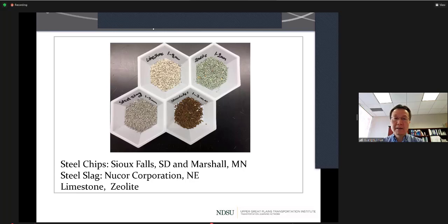So during the batch experiment study, we selected 4 materials, including limestone and zeolite. These are the 2 natural materials that are readily available. And these 2 materials have been evaluated as stormwater filtration materials for phosphate removal. And we want to know whether these 2 materials can also remove E. coli or not. In addition, we select 2 recycled steel byproducts, steel chips, and we collect material from 2 recycling companies, one located in Sioux Falls, South Dakota, and the other in Marshall, Minnesota. So we collect recycled steel chips from 2 locations. And also we collected steel slag from a steel making company, Nucor Corporation in Nebraska.